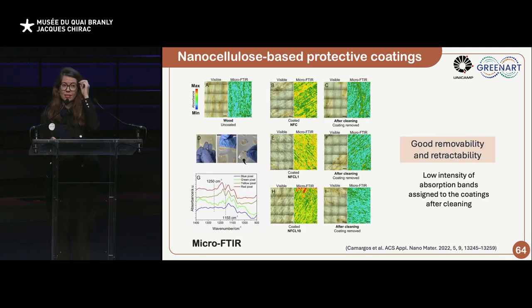And here we also assessed the removability of the coating, as it's important to have the retractability of these materials. And the results are interesting as well, because here we have the mapping of the surface before coating application. Here are some mock-ups with the coating on the surface, and then we were able to remove most of the coating with the application of a water-loaded hydrogel, for example, but you can do that with a cotton swab, with water as well. And the mapping profile after this cleaning is quite similar to the mapping profile before cleaning.